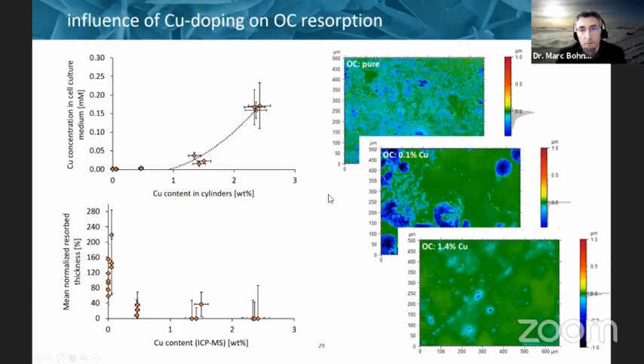So these samples were placed in the osteoclast study. This is the standard image that we normally see. The blue would be the holes that are created by the osteoclast. With a bit of copper, you see a completely different behavior, with kind of wells or big holes that are created, but in most of the surface, nothing else. And then if you add more copper, then you basically kill the osteoclast and there's no resorption anymore.